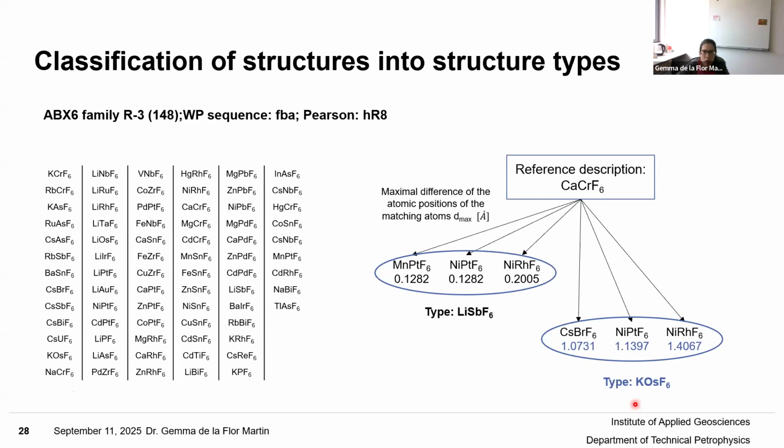You already know that two structures are defined as isoconfigurational, or that they belong to the same structure type, if the structures are isopointal, and for all corresponding Wyckoff positions, both the crystallographic configurations and the geometric interrelationships are similar. And again, this term similar is not specified, and that's why it's so difficult to quantify and implement in algorithms for automated computer searches. So in fact, the program COMPSTRU can be applied in these types of problems.